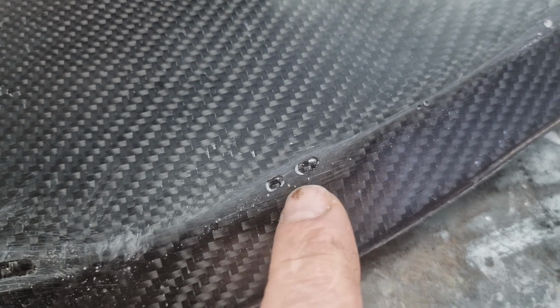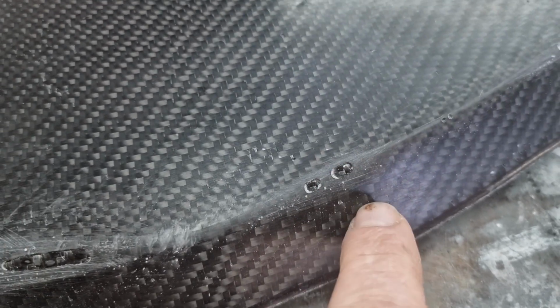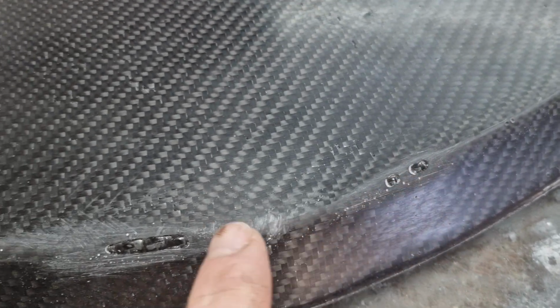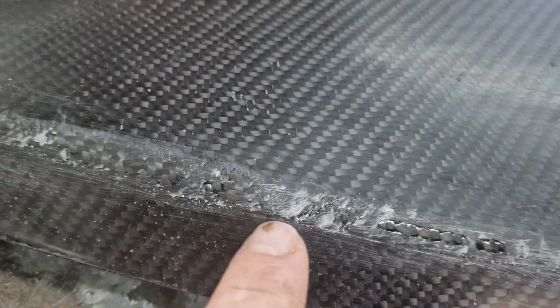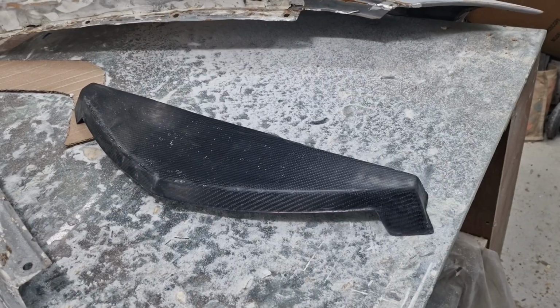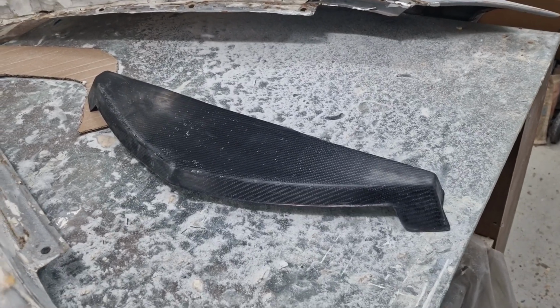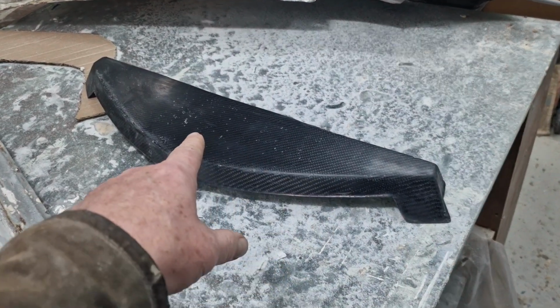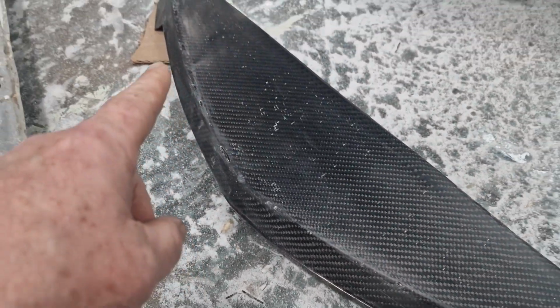Quick trim of the edges and cleaning up shows two types of problems. One, bits where the resin didn't actually stick, and two, these kind of crystally flaws within the resin itself. Both need resolving. Actually, there's a third type as well. These white marks on the flat surface, they're actually gaps in the resin, the same as the first ones I showed you, but they look a bit different because they've got this sanding dust in them.